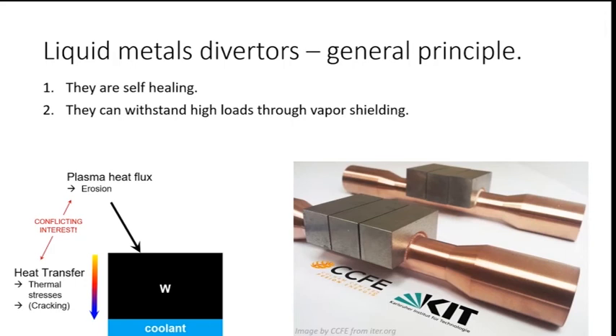But nevertheless, there is a sort of inherent limitation. The problem is that the plasma will erode the tungsten. And so to have a long lifetime, you want to start out with a nice thick block, and this will get thinner over time. But okay, if you start out with a thick block, you will have some lifetime. But at the same time, you want to keep the block from melting. And well, to keep the surface cool, you want to make the block thin. That is how thermal conduction works. A thicker block will get hotter on the top. So you want to start out with a nice thin block from this perspective, not a thick block. And this is an inherent conflict of interest that you can only go so far in compromising.